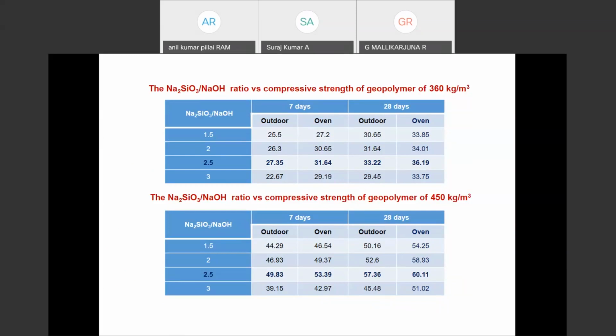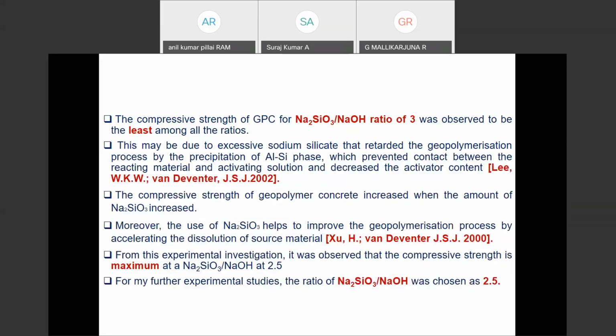We tested 360, 420, and 450 kg per meter cube. We got the maximum strength at the ratio of 2.5 for 360, 420, and 450 also. And why? Because if you go for a higher concentration of sodium hydroxide, definitely the strength will increase. But in order to get the maximum, or to improve the polymerization process, we have to consider the required amount of the sodium silicate solution for the study there.